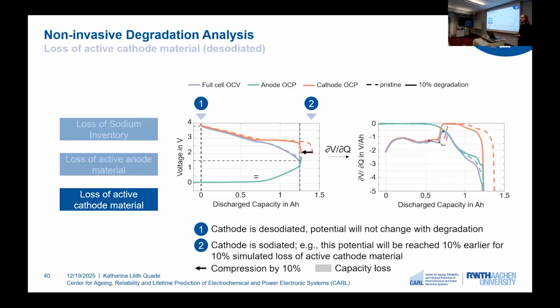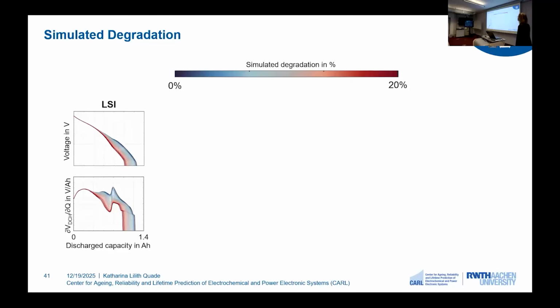And we now repeated these simulations not only for loss of active cathode material in the desodiated state, but for all other degradation modes, and also continuously for a degradation of 0% to 20%. Let's have a look at the results. Here we can see the voltage curve in the case of loss of sodium inventory, as well as the first derivatives below. And we can see in blue here, that is the no degradation case. And in dark red, we can see the 20% simulated degradation case. And we can also have a look at the first derivatives, and we can also include the capacity loss that results from a 20% simulated degradation.